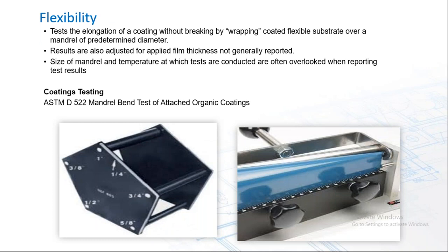Flexibility, once again, is important if we're talking about concrete and wanting to wrap our coatings around sharp edges, radiused edges. Obviously, the ability of a coating to wrap a smaller radius and maintain its integrity is much better than something that wraps a larger radius. But typically on data sheets, you're not party to know whether that's a quarter of an inch or a 1-inch mandrel that it's passed on.